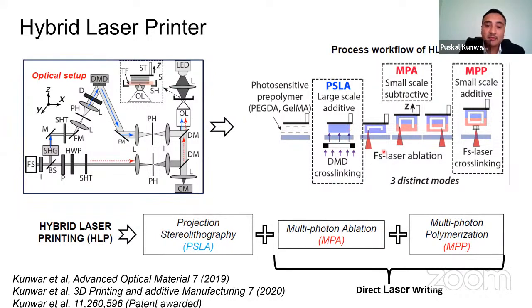Next you bring in your femtosecond laser ablation or direct laser writing beam and ablate structure within the previously cross-linked structure. Now you do an iteration, and you can complete the printing process. You could also do an additive approach with the same thing if you decrease the laser beam intensity. So basically now we have a hybrid laser printer, which is a combination of projection stereolithography, or optical projection lithography, and also direct laser writing based on MPA, multiphoton ablation, and multiphoton polymerization.